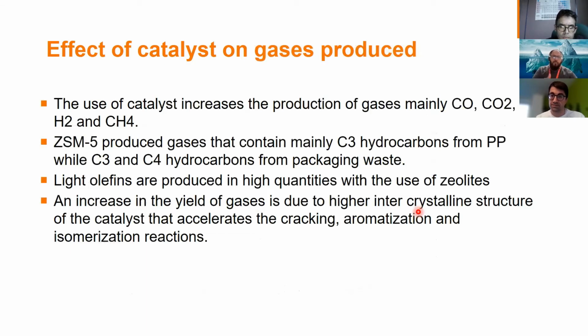So what is the effect of the catalyst on the gases produced? Basically, they produce gases, mainly hydrogen, methane, carbon monoxide, carbon dioxide, depending, of course, on the polymer used. For instance, PET can produce a lot of carbon dioxide and carbon monoxide. Polyolefins tend to degrade into very olefinic types of gases. For instance, this ZSM5 zeolite can produce gases that contain mainly C3 hydrocarbons from polypropylene and C3 and C4 hydrocarbons from packaging waste.